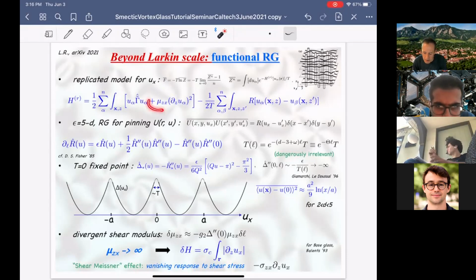The other ingredient is the elasticity, which does not get renormalized except for one particular component of it, the shear modulus mu zx, for non-uniform distortions of the crest of this vortex lattice, or shearing of the vortex lattice in the zx plane.